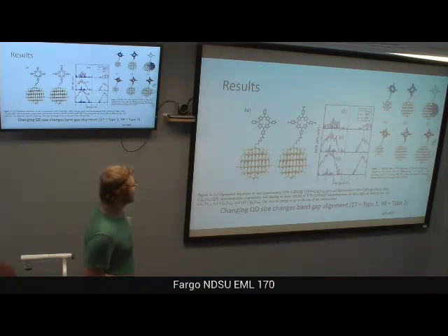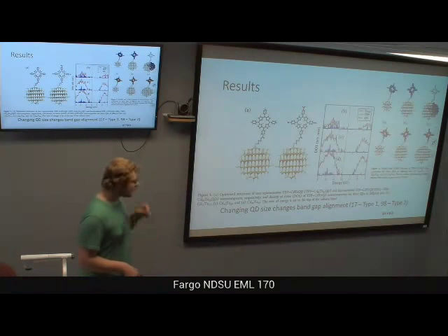Okay, yeah, I understand that, but in the math, what is it all taking into account? It's more what I'm curious about. So it takes in absorption and thermal loss. So this is the quantum yield of absorption, and then it's multiplied by the solar spectra. So then you can get an average or the sum of every photon coming in, how many quanta can be made, and then you integrate that over this.